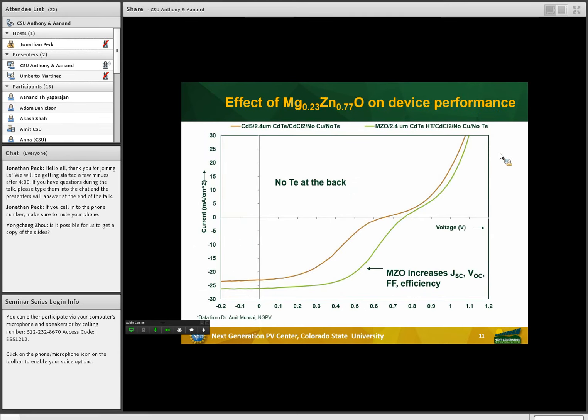And the motivation for this research using MZO as a window layer is shown below. Anthony spoke earlier about the effect of tellurium, which eliminates the kink and results in high-performing devices. This plot shows the effect of MZO before the incorporation of tellurium at the back. The brown curve